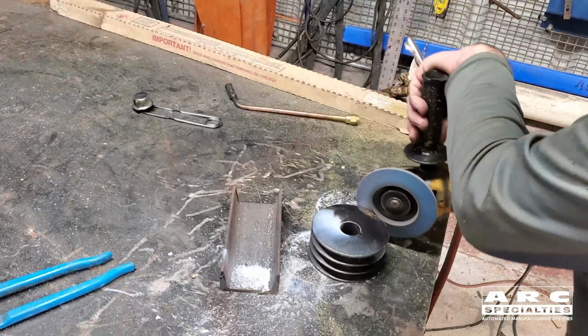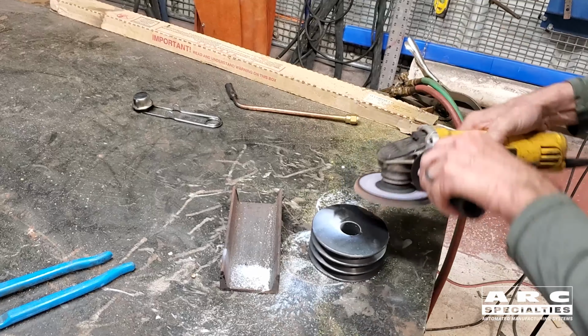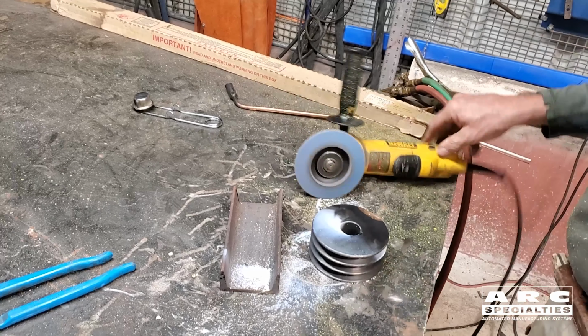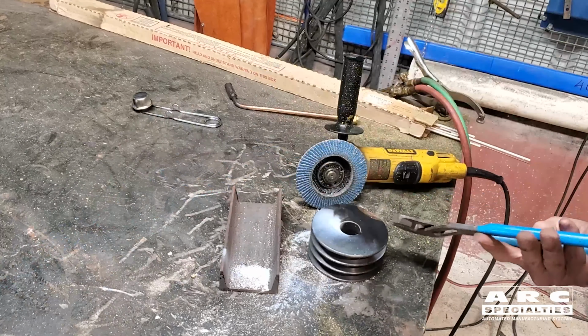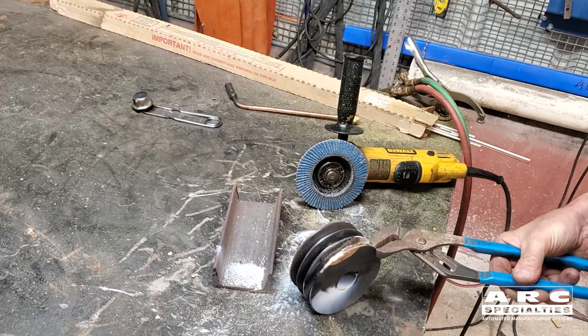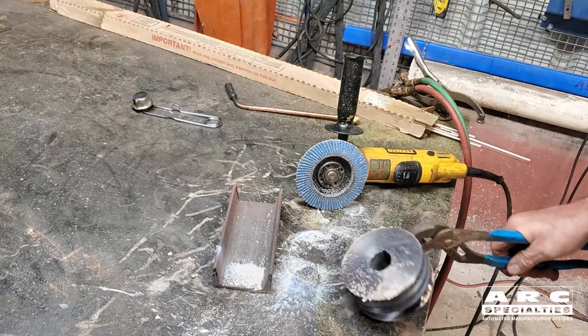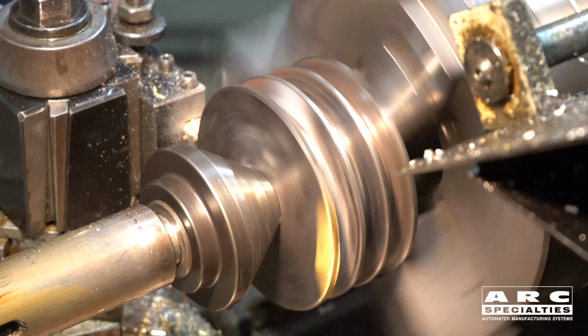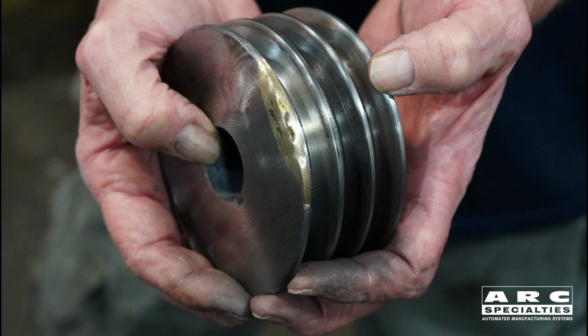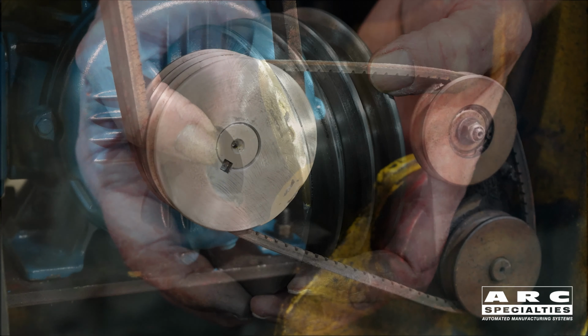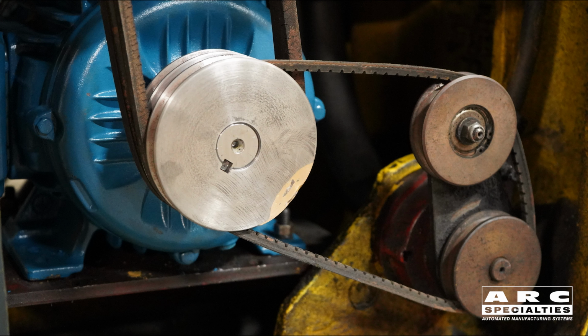Once I thought I had enough brass on the part, we let it cool for a while and I hit it with a sander. You can see there's a few pinholes in it. Brazing is a perishable skill and I'm a bit out of practice, but these holes weren't going to affect the function of this pulley, so we wrapped it and allowed it to slow cool. After the part had cooled completely, Henry chucked it in one of our lathes and machined the groove to fit the V-belt. Here you can see it finally installed back on the lathe, ready for operation.